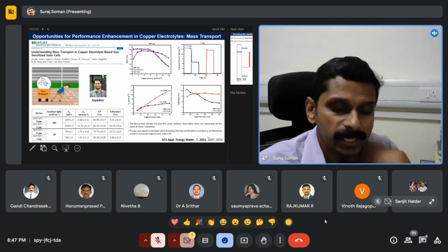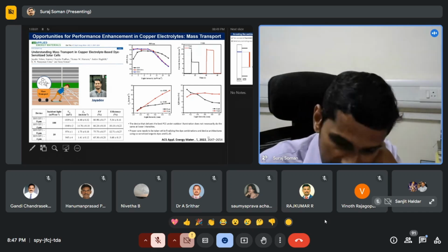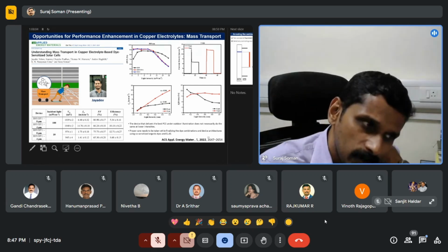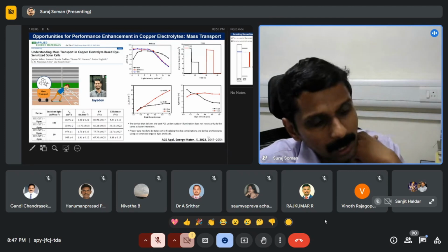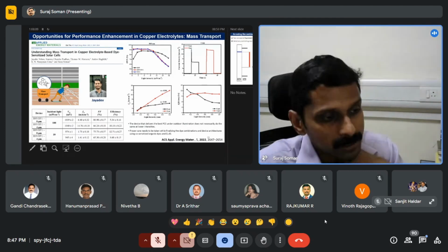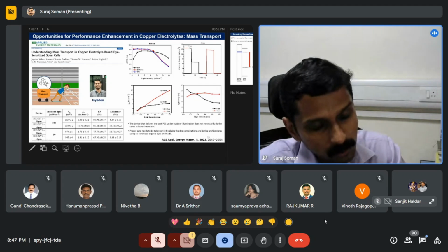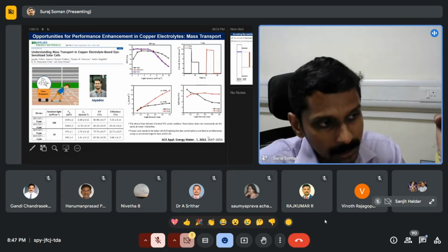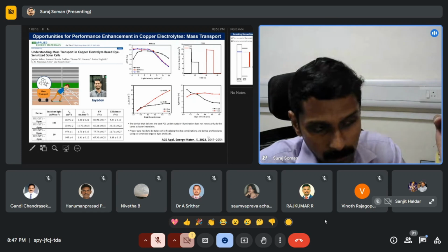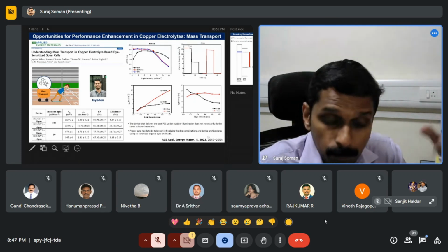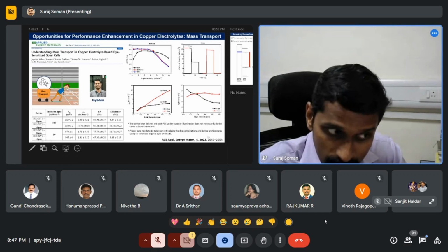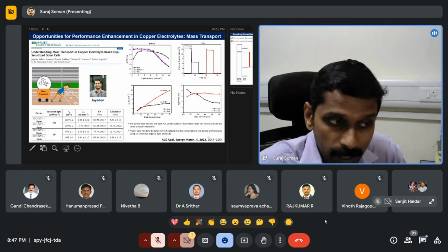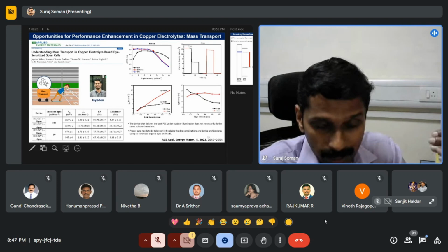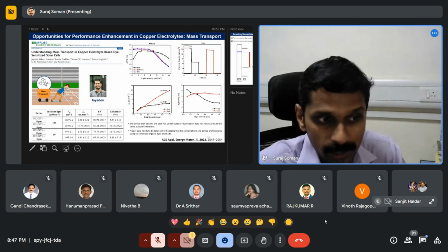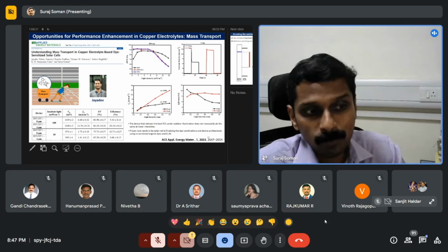What he did was make electrodes of different thickness. It is a very interesting study: under higher illumination intensity, 100 milliwatt per centimeter squared, which is the standard one sun condition, the device with a thinner electrode, around 4 micrometer, delivered a performance around 10%. But at lower intensity, like one-tenth of the light intensity, 10 milliwatt per centimeter squared, the thicker electrode performed well, giving close to 13% efficiency.